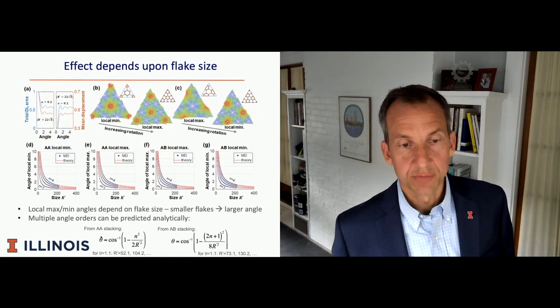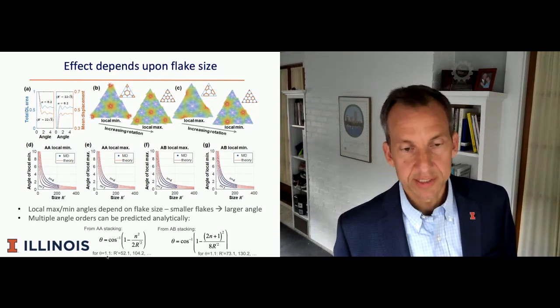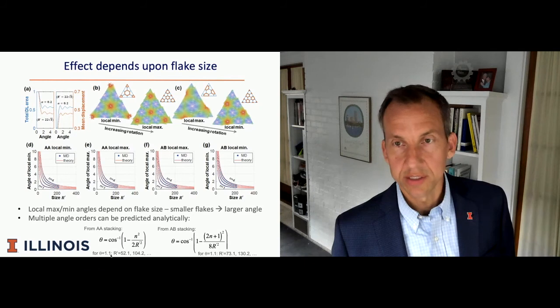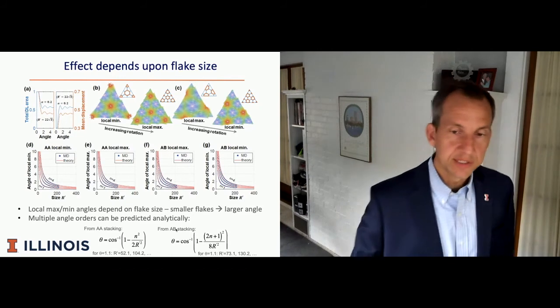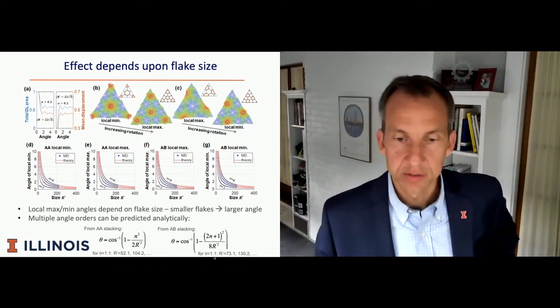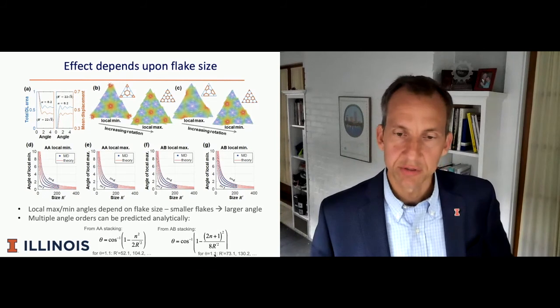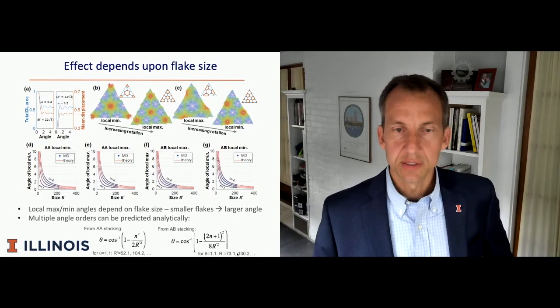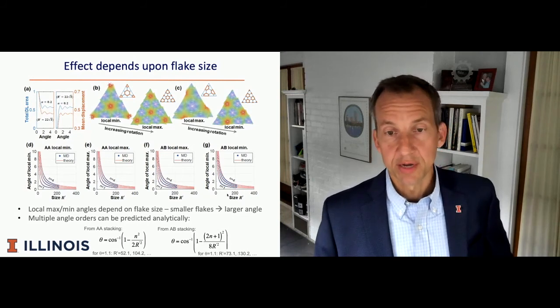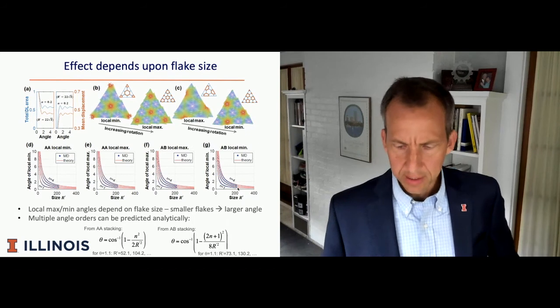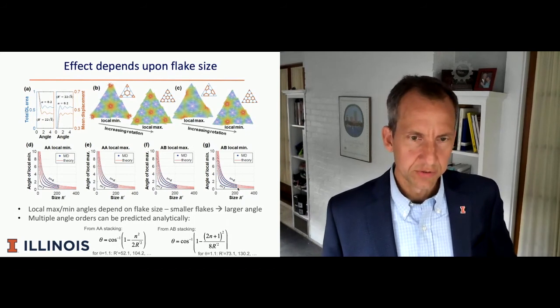For example, if we start from AA stacking, we can predict precisely what it takes to get a 1.1 degree twist angle in terms of the size of the flake. Or if we start from AB stacking, we can say if we want a 1.1 degree twist angle, and remember that's close to the magic angle in graphene, we know exactly what size flakes will give us those angles. The other thing to point out is that we have really precise matching between the atomistics and the analytical model. This is a credit to Xu Zheju, the postdoc who worked on this, and I think it's quite an interesting result.